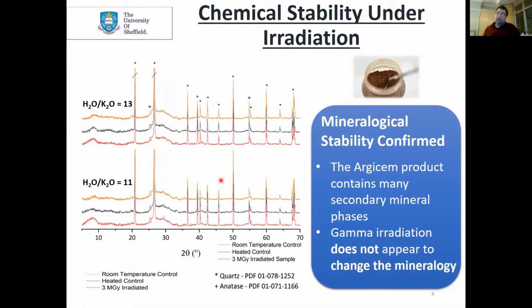Now, if we flick over to the flash calcined RGSEM system, as it's known, this red metakaolin, this is incredibly crystalline in itself and has large amounts of quartz in that sample. So by having this large amount of quartz, it does appear different—you can see there's mineralogy there, but there isn't any change in it.